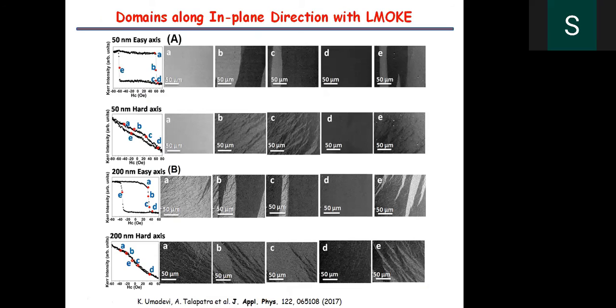To complement the results we have seen earlier, we have also done magneto-optic Kerr microscopy studies using longitudinal MOKE, and the studies show strong band domain patterns, and the material is found to be anisotropic. That means along the plane of the film also, if you rotate the film to different directions, you see different kinds of domain patterns. Along the easy direction of magnetization, you see a band domain pattern. When you go towards the hard direction of magnetization, you see ripple-like patterns.